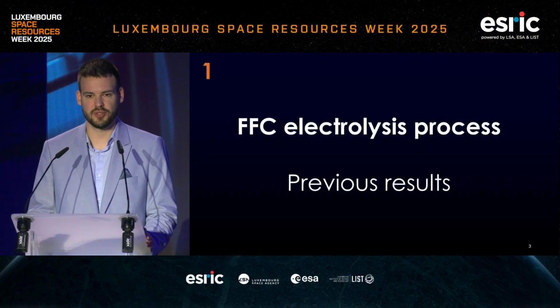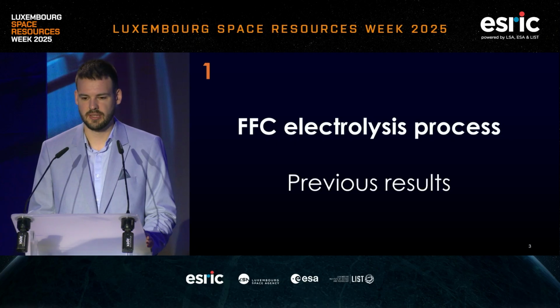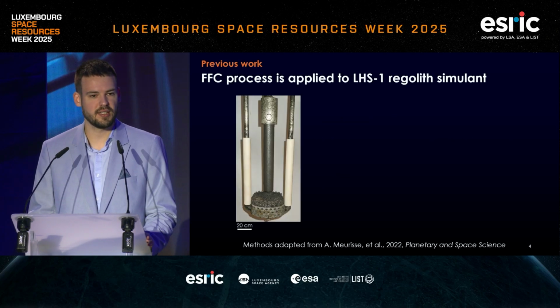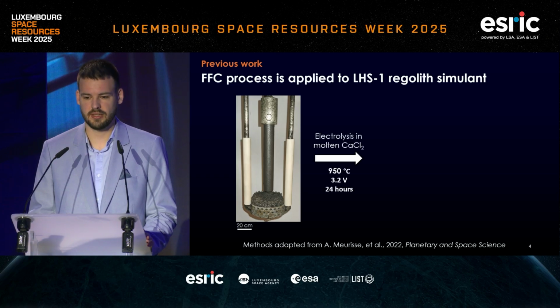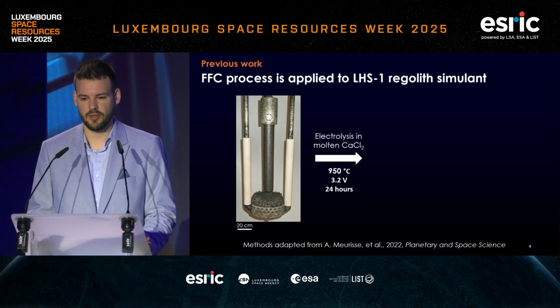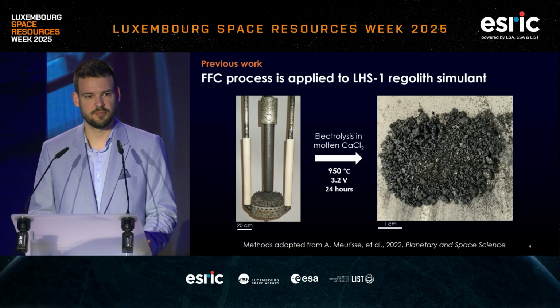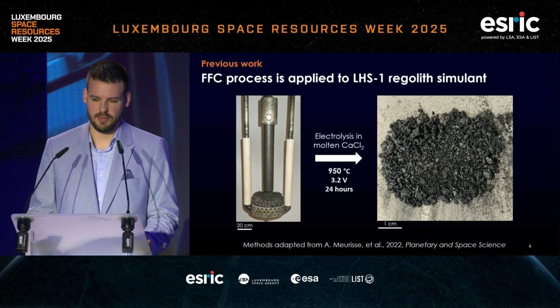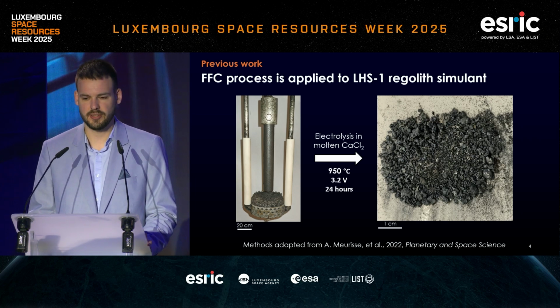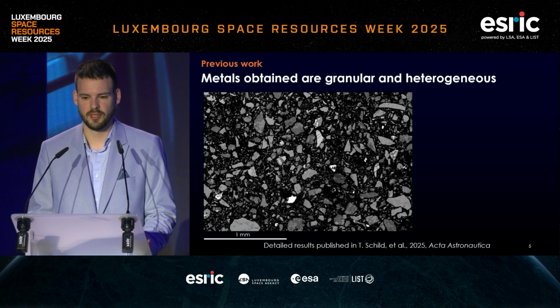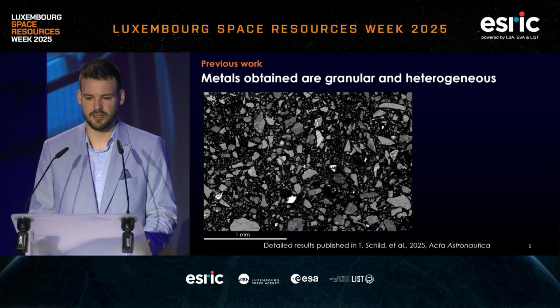So to begin with, I'm going to do a very quick summary of my presentation from last year, which was all about the characterization of those materials. So what we did, we ran the FFC process at a lab scale on LHS1 regolith simulant. And when you do this, so you electrolyze it in calcium chloride, in our case for 24 hours, and you end up with this kind of material. Metallic powder or granulate that looks very heterogeneous as it is, and even more so if you take it under the microscope. So here you can see the abundance of all the different metallic phases that you have in there, all mixed together. I'm not going to go too much into details about that.